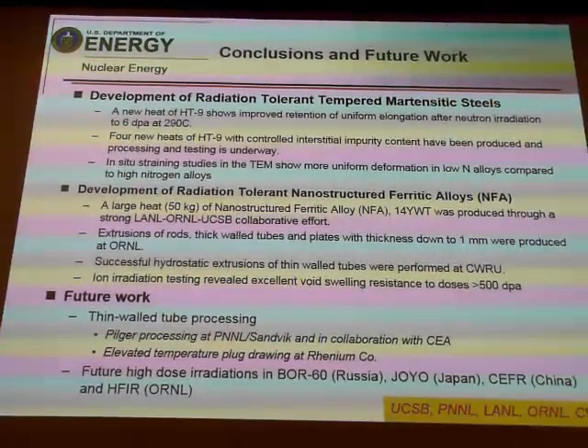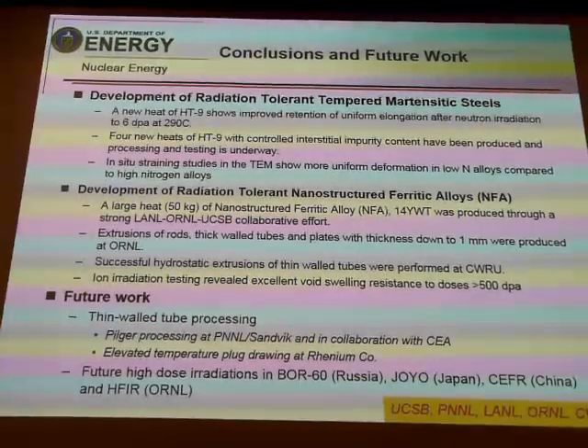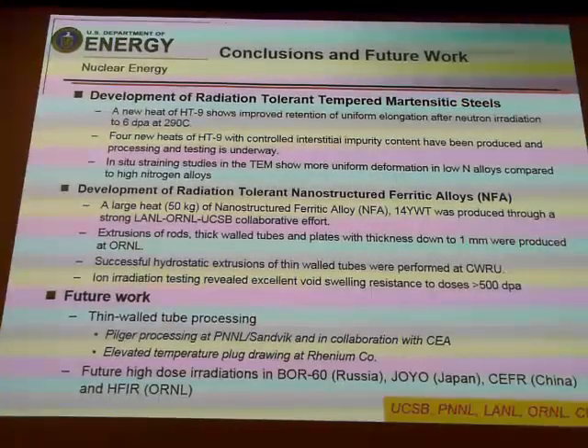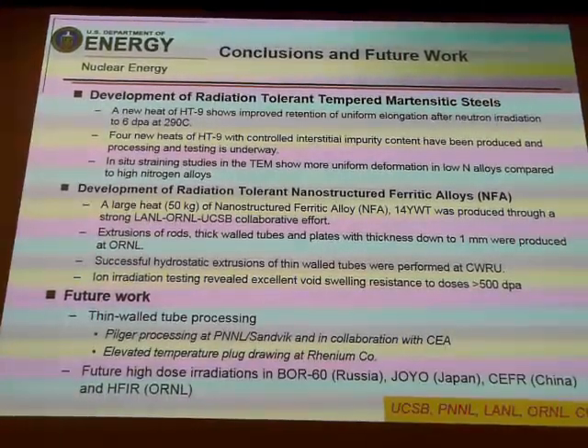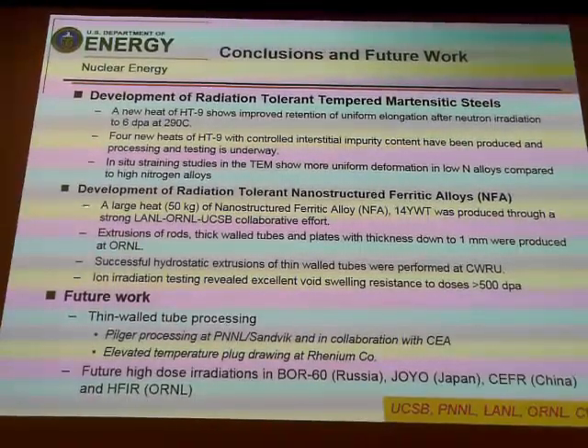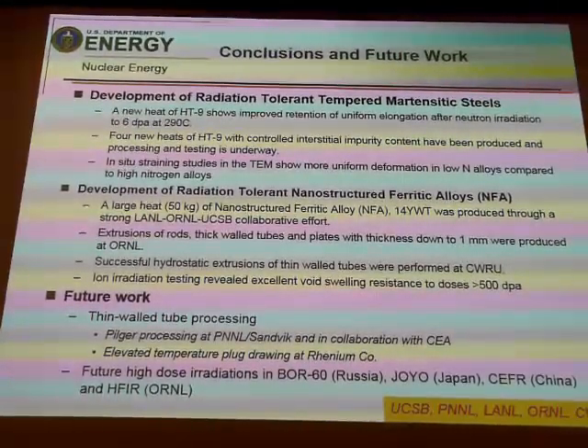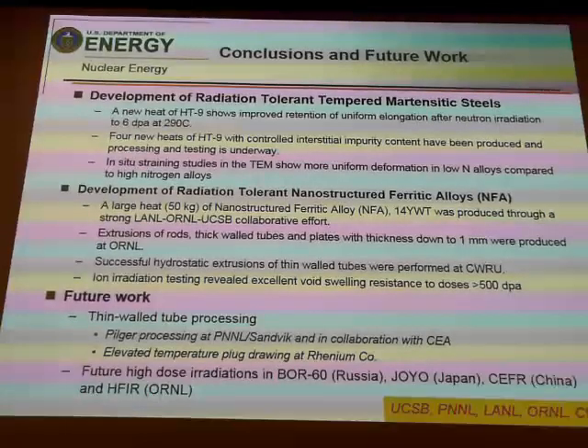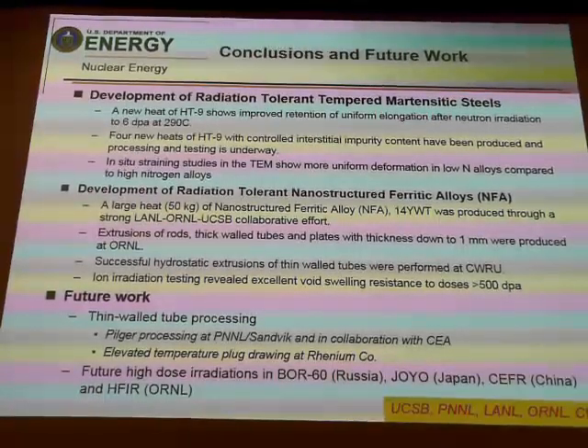Ferritic steels and HT9 in particular were the darling of the fusion materials community for about 10 minutes in the early 80s. You remember what happened, why they're no longer as popular? I don't do a lot of work in the fusion area, but maybe you can add to it as well, Mike. But I think one of the issues that fusion has that they don't have in fast reactors is that you have a large buildup of helium along with displacement damage, at the rate of 10 appm helium per dpa. Right. And what the tempered martensitic steels don't have is a fine oxide dispersion that can help you to manage the helium. But the ODS steels do. So I think partially they've moved toward that direction. I'm not sure if there's other reasons why they may have.